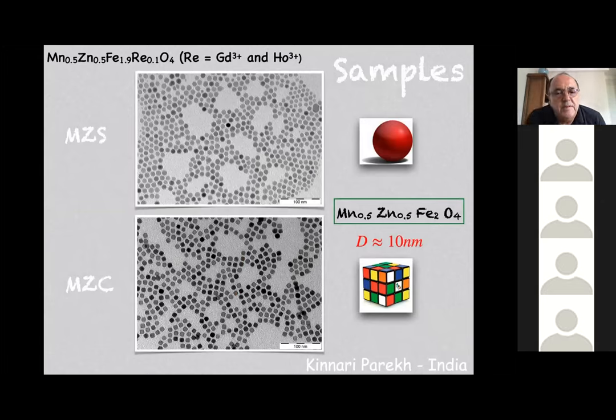Well, these are basically the types of ferrofluids that we investigated during this research in our labs in São Paulo. Some of them are made of manganese zinc ferrite, Fe2O4. We have spherical particles here with typical dimension of 10 nanometers, but we can also have this type of cubic particles, with the size of this cube also about 10 nanometers. They are not too polydisperse, but we can introduce all these parameters in the analysis of the results we will have from the optical point of view and also from the X-ray scattering point of view.